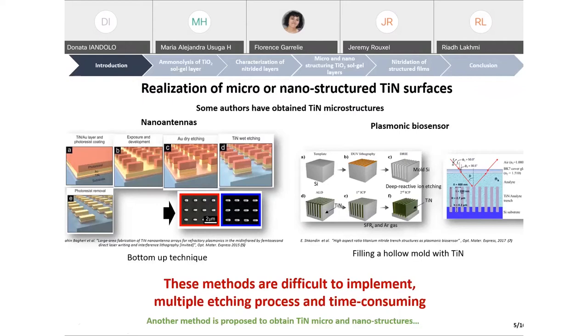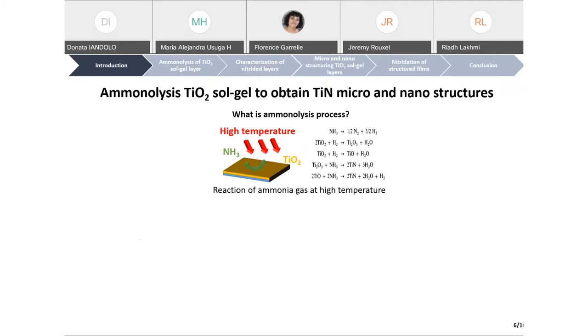So there exists another method to obtain titanium nitride micro and nanostructures. This method is the ammonolysis of titanium dioxide sol gel to obtain titanium nitride micro and nanostructures. But what is the ammonolysis process? The ammonolysis process is a reaction at high temperature. To obtain titanium nitride, a reaction is carried out between ammonia gas and titanium dioxide at high temperature.